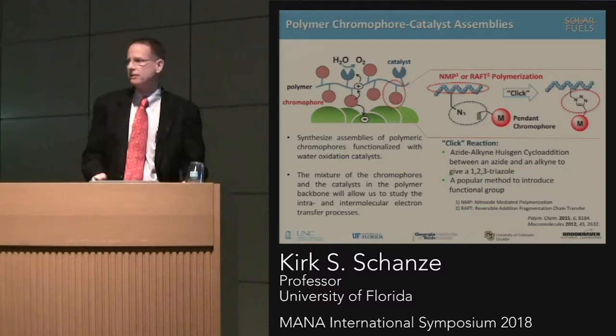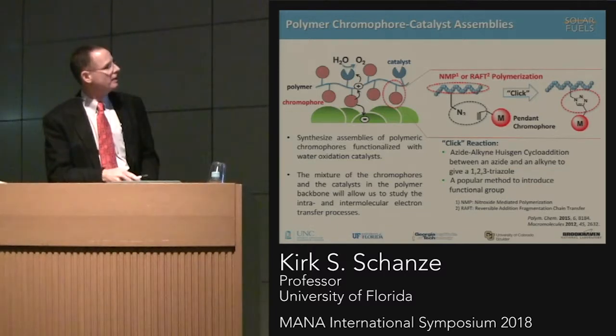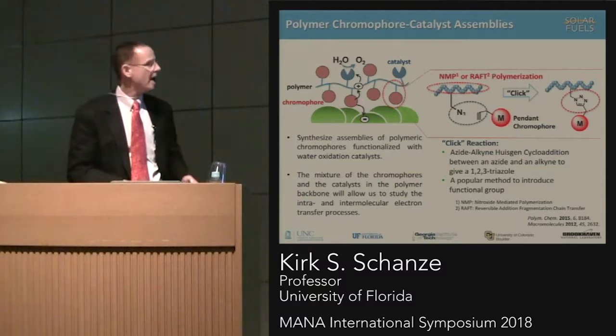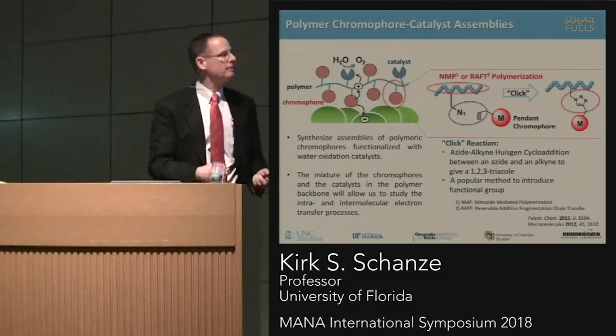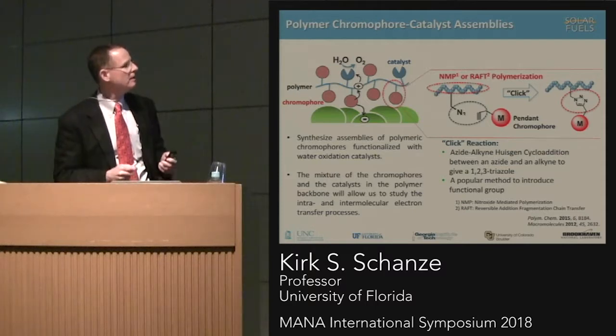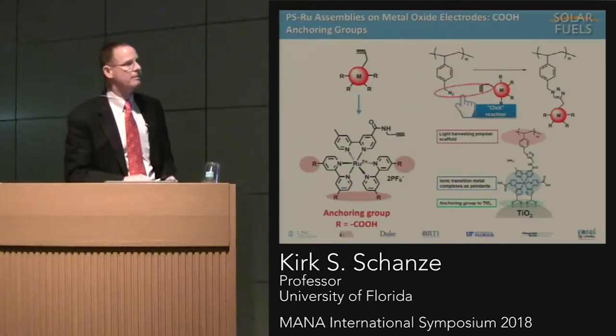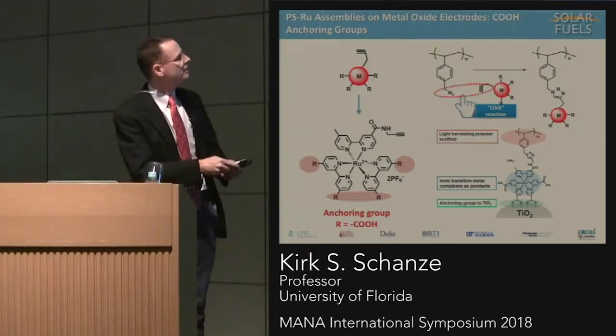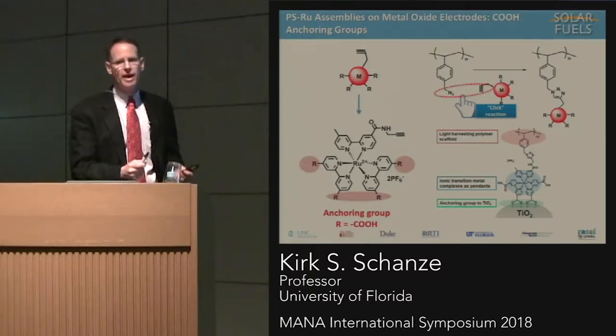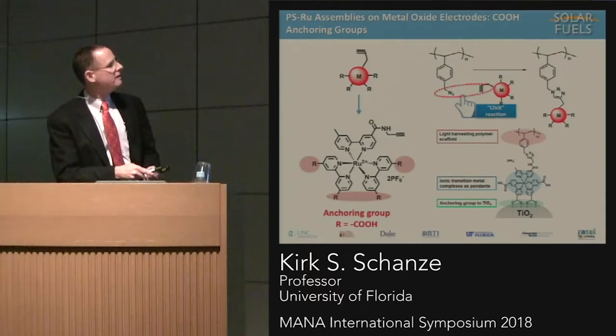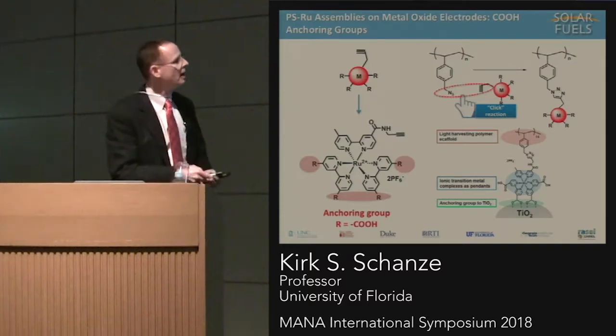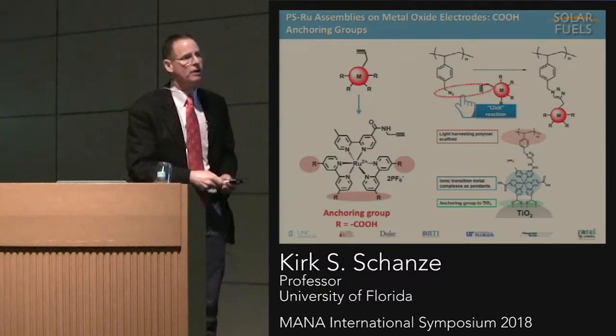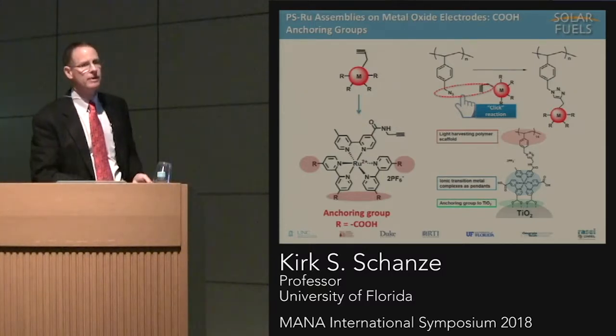I'm not going to talk about synthesis at all, but the chemistry that went into developing these reactions took 3 to 5 years of several postdocs and graduate students. But the accomplishment is that now we're able to take a given polymer with a controlled molecular weight or size. It's functionalized in a way that we can very easily attach chromophores to it. For example, shown here is this ruthenium complex that's functionalized with anchoring groups. We can make the polymer that has these functionalized rutheniums and then use it to anchor the assembly onto the